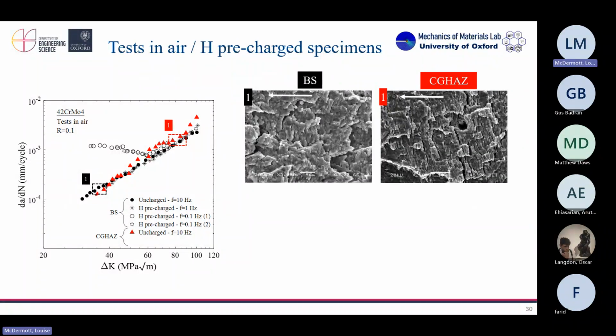And it's very interesting to see the effect of the frequency. So when I do fatigue, I can choose the frequency, okay, with some pulling. And what we see is that if we go to high frequencies, like closer to the ones of the samples that didn't contain any hydrogen, the behavior is exactly the same, but I have to reduce the frequency by a couple of orders of magnitude to really see an effect of hydrogen there.